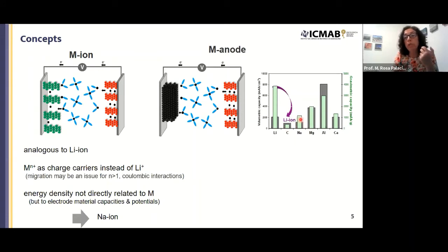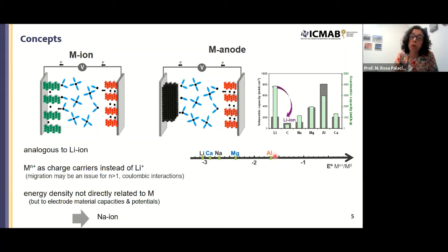So sodium also has issues with dendritic growth, but then if we could use multivalent metals like magnesium, calcium, or aluminum, the capacities would be higher, especially volumetrically, because lithium is not very dense, and especially for aluminum, if one could exchange 3 electrons per mole of metal. But energy is the product of capacity and voltage, so let's have a look at the reduction potential of those metals. For aluminum, it is moderate, so it is not that interesting. Magnesium is slightly lower, but then what is interesting is that calcium is very close to lithium and sodium, so very negative standard reduction potential. So promise of very high energy density if we are using metal anodes.